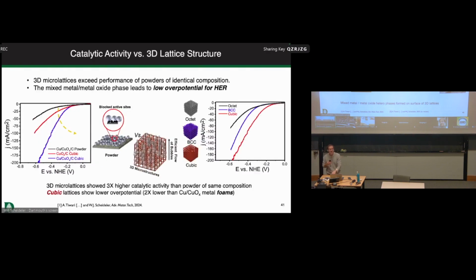We were focusing on both HER and OER, so these are two different reactions that we could perform electrocatalytically. And if you haven't seen a plot like this, what we're trying to describe essentially is how much overpotential or how much additional voltage we have to apply to be able to generate a large enough current. The level of the current generated essentially corresponds to how much oxygen we're evolving or how much hydrogen we're evolving, depending on the reaction that we're running.